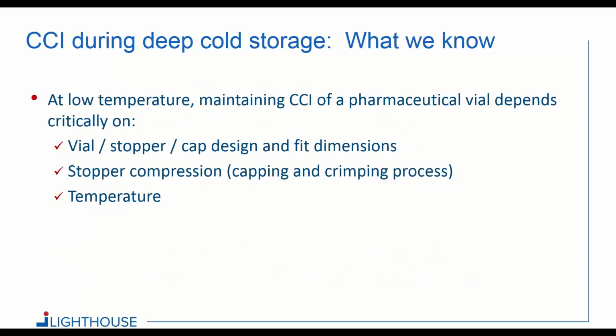So what do we know? What have those 5 or 6 years of more intense studies shown? At these low temperatures, maintaining CCI of a pharmaceutical vial depends critically on a few things. First of all, the primary packaging components: the specific vial stopper combination and the vial, stopper, and cap design and fit dimensions. How do these components fit together and stack up? Number two, the stopper compression. How well is this vial being capped and crimped? And thirdly, of course, temperature, specifically a temperature range around the glass transition temperature of the rubber stopper. We'll get more into that in just a minute.